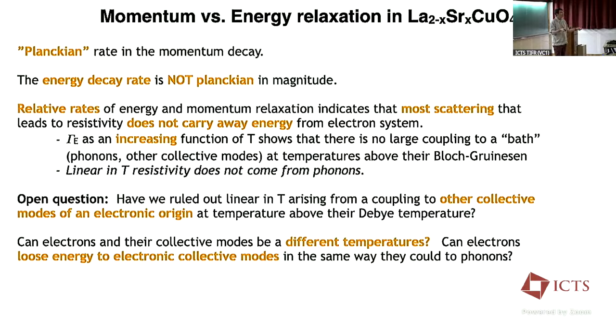But electron-electron scattering doesn't take away energy from the electronic system. It just reorganizes energy within the electronic system. The fact that gamma E, the energy relaxation rate, is an increasing function of temperature shows that there's no large coupling to some kind of bath at temperatures above their Bloch-Grüneisen temperature. In other words, we're below the effective scale of the bath that the electrons are coupling to and losing energy to. So you're at temperatures which are small compared to the effective scale of the bath.